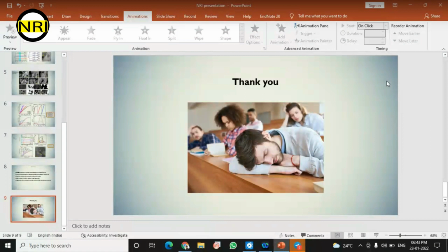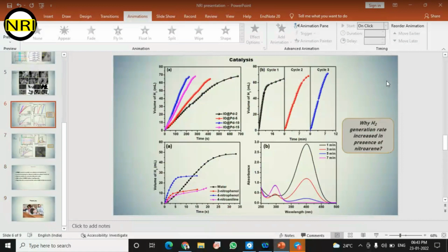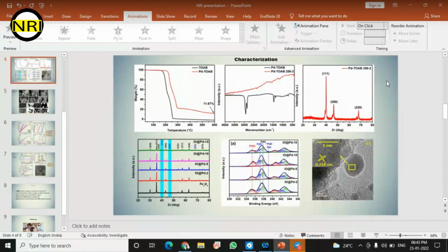One more thing is that you can see this palladium XPS here, the second row middle graph. I didn't know that we can deconvolute this palladium into four peaks. One of the reviewers for this work suggested that the palladium XPS was not characterized well. So I had to find what other characterization I could do with the palladium. Then I came to know that we can fit the palladium peak with four or five peaks. This was also a very good learning from the reviewer comments. These are some difficulties I faced during this work.